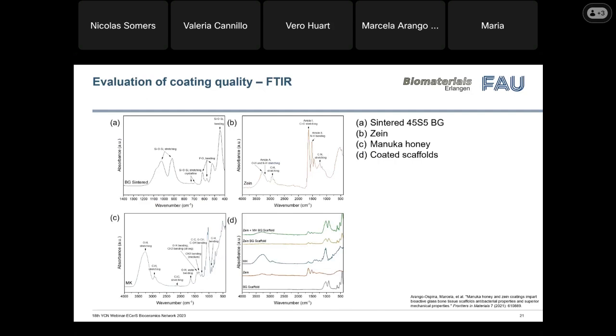And of course, we also analyzed the coating with FTIR. In here, we can observe that for the glass spectra, we have the typical silicon-oxygen bonds. Then for the zein spectra, we have the typical peaks for proteins with different amide groups. And for the honey, we can see peaks which are characteristic of carbohydrates. But our idea was to see if we could identify the presence of honey in the scaffolds with this method.